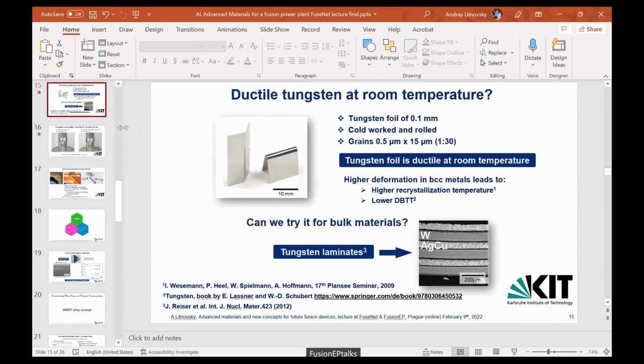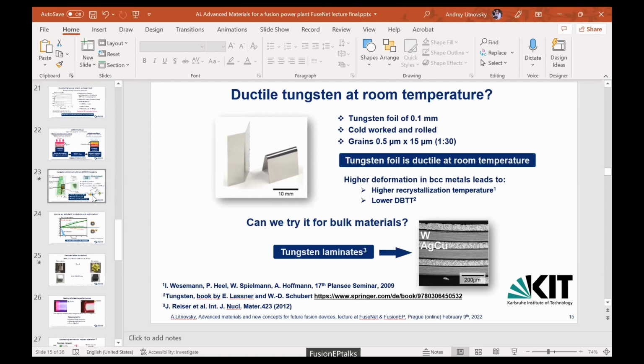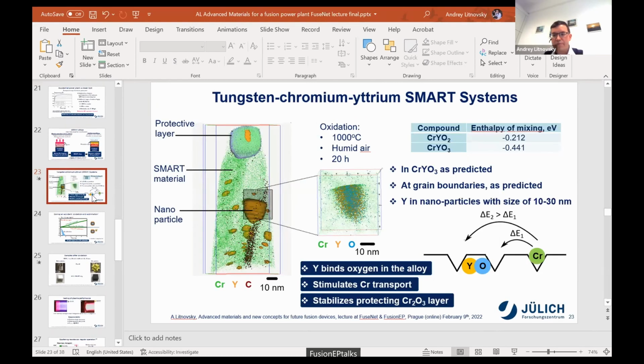Last question. So yttrium, when you add yttrium to alloys, it may make materials magnetic. Is the alloy magnetic or not? It's a simple question. Thank you. It will not be magnetic because we have 0.6% of yttrium. So this is actually the key effect here: I mean, here we can see it's quite a lot, but in total it is 1 atomic percent. So it's really in very tiny amount, located in very precise locations, and doing, until now not fully explored, very interesting job in many areas.